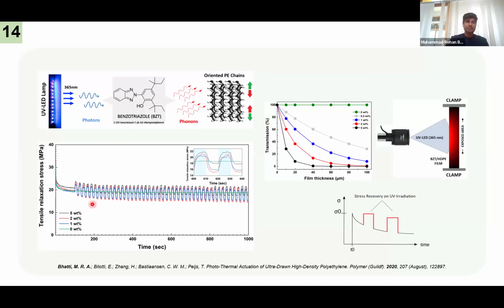As you can see over here, as soon as the light turns on, we keep it on for 10 seconds and then 10 seconds off to see the reversibility and rapid effect of the photoresponsive agent. As you can see, we achieve a very rapid and reversible response. We actually used 3 or 4 different percentages of BZT to see if we can enhance the effect. Actuation is triggered by the light which was absorbed by the BZT and transformed into heat. We were able to achieve a very high actuation stress, around 20 megapascal. And that is because of the Young's modulus of the oriented polyethylene chains and the negative coefficient of thermal expansion. That is what we believed at that moment.